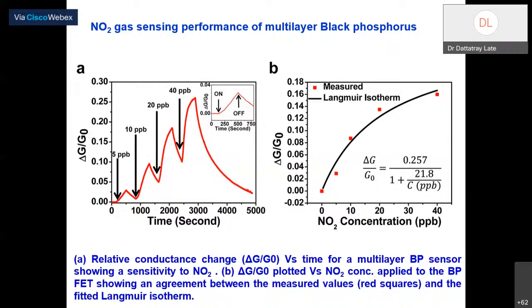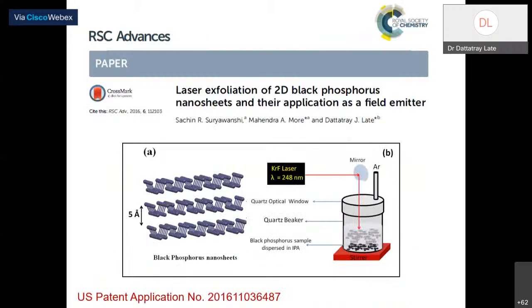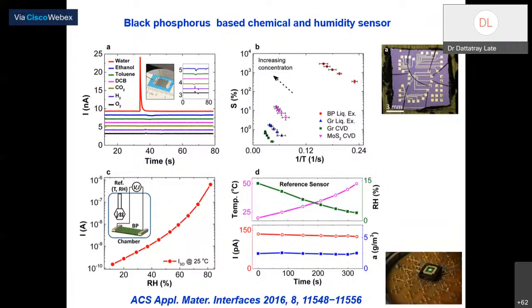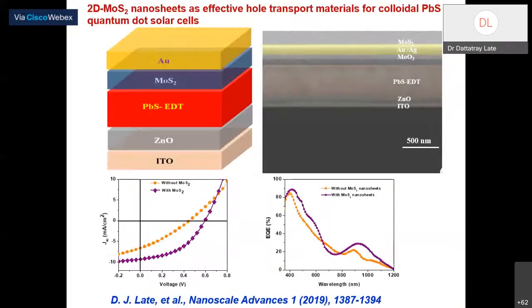Again, the gas sensing mechanism is similar. The charge transfer is the origin of this particular gas sensor based on this material. Also shown you earlier that this black phosphorus nanosheets can be synthesized in just 1 second or just maybe few seconds to 1 minute time, depending upon how much thickness you needed. Of course, then we tested it for gas sensor, photo detector application.